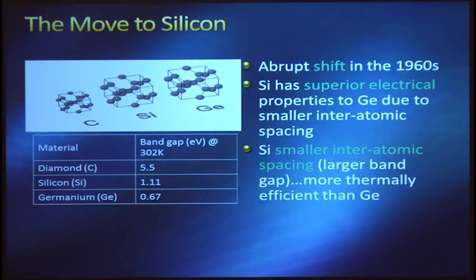And what we notice is that germanium, silicon, and carbon all arrange their atoms in a lattice structure known as the diamond lattice. And in the 60s, there was an abrupt shift away from germanium to silicon over the duration of just a few years. And that's because silicon has superior electronic properties as compared to germanium, largely due to smaller interatomic spacing. Right? The atoms are more closely arranged in silicon than they are in germanium.